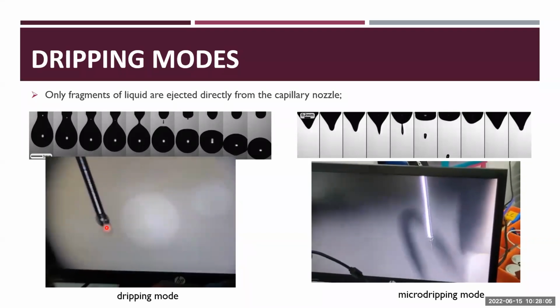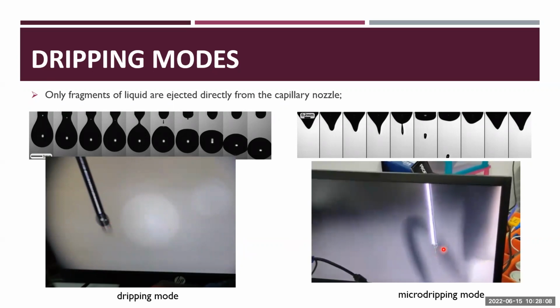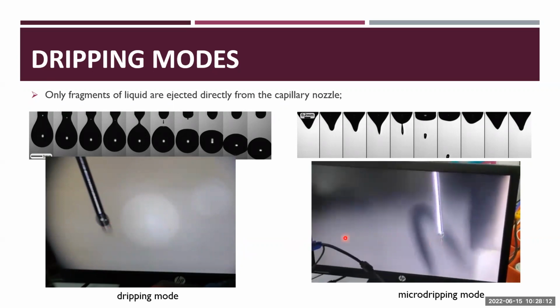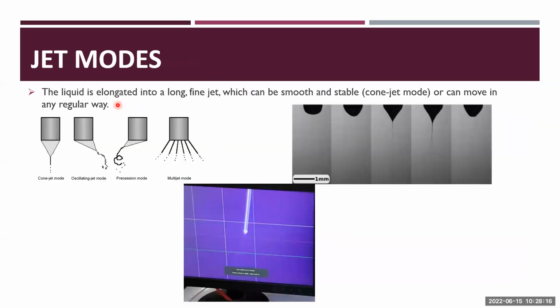We control it with the voltage. This is a micro dripping mode we have done in our lab. And the second mode is the jet mode. In the jet mode, the droplets do not drop by gravity, but instead they spray. After building up this cone jet, the liquid starts to flow. Then it will be separated into particles because the liquid repels itself because of the high electrical field, and starts to spray. And because of the charged particles, they repel each other and make that cone. So we call it cone jet mode.